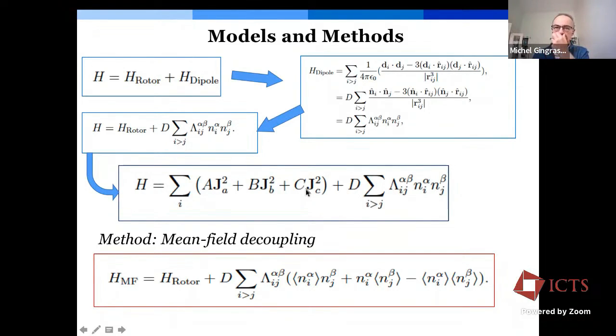So the method we took to survey what's possible in terms of phase diagram for these systems is a simple mean field or Hartree decoupling of the dipolar term, mapping this problem onto a self-consistent Stark effect, and solving for the critical temperature and the internal polarization of that system and constructing phase diagrams.